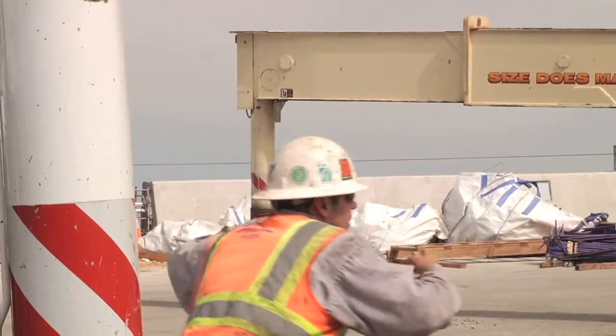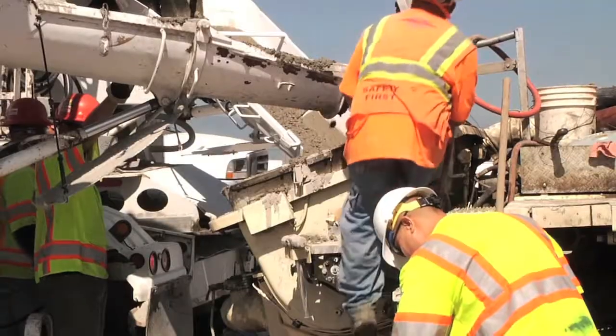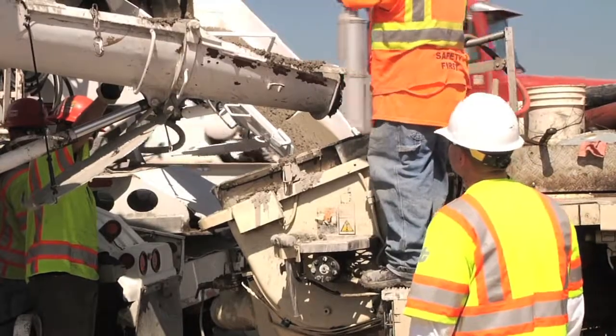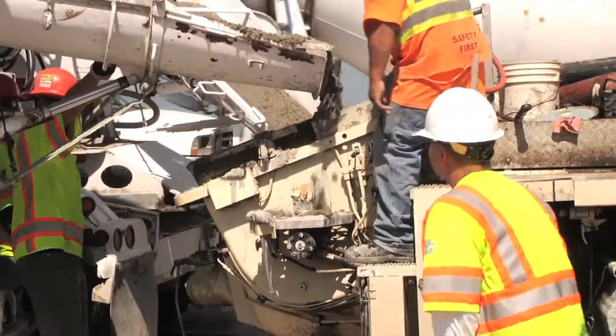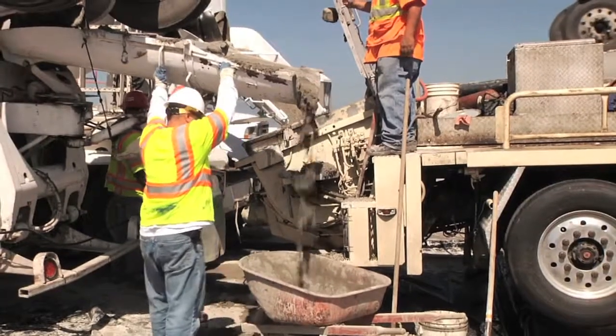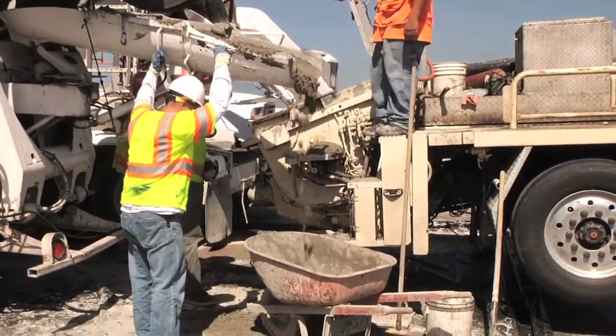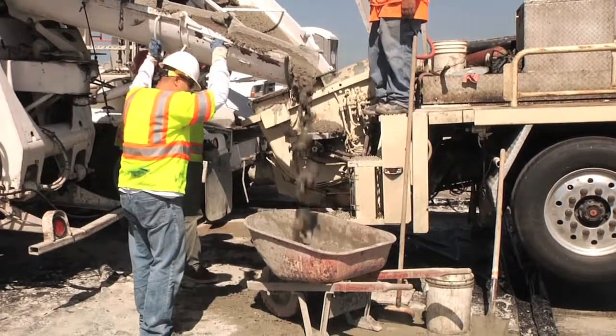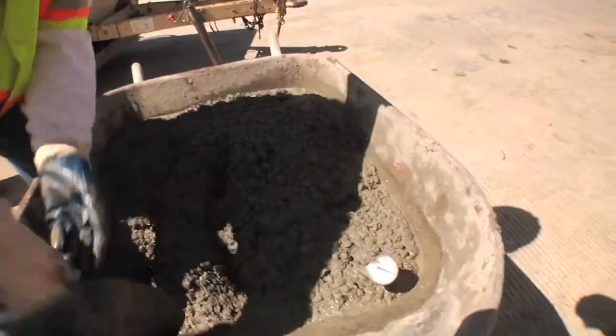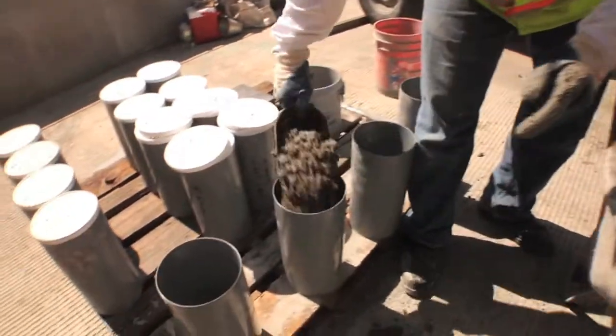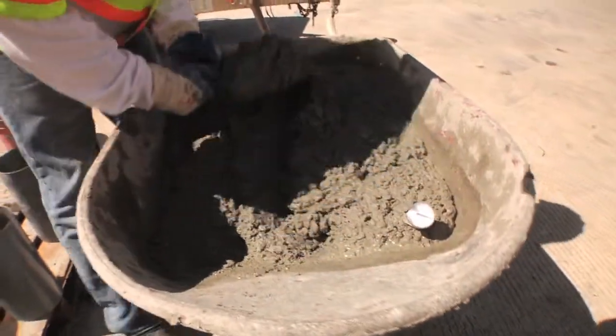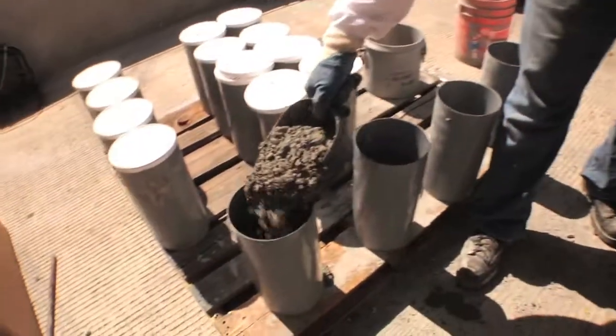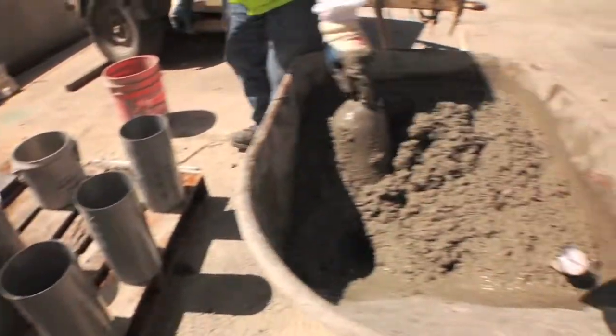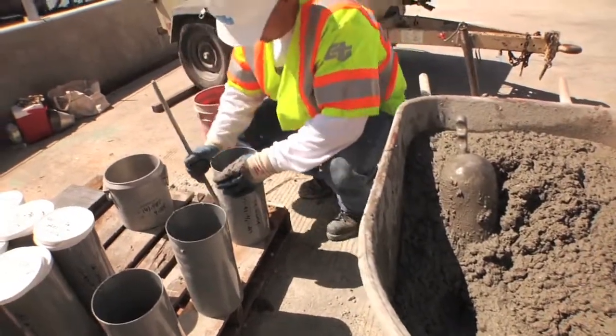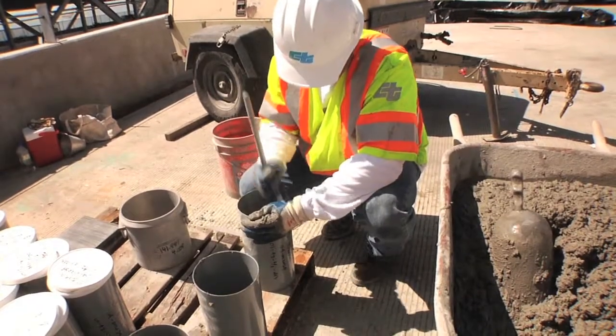As the machine is frantically set up, the waiting concrete mix from each concrete truck is tested by Brandon Young. He's an inspector for Caltrans, and he's the one monitoring the concrete to make sure that we don't have to reject any of the batches. But with that little bit of a slowdown, we had to make sure that the concrete didn't set up. So a number of factors go into determining whether a mix is good. This one was fine because although the temperature is getting higher, there's still plenty of slump. There's an admixture in this that's actually keeping the temperature low so that it can make it through the entire pour and then set up as it was designed to.